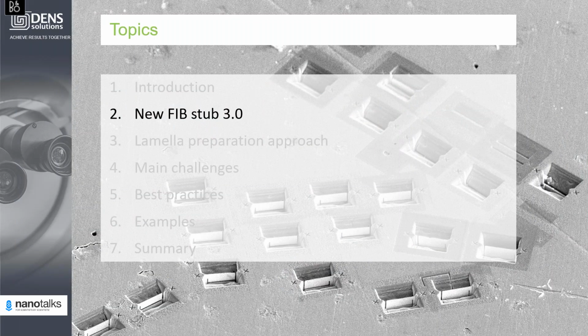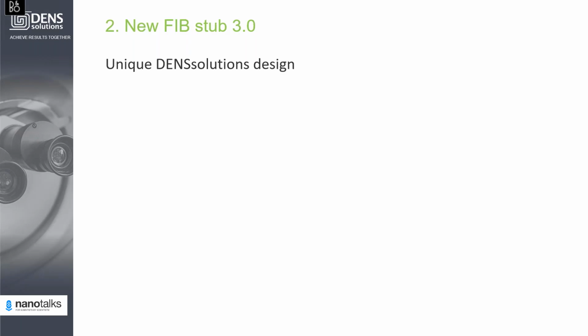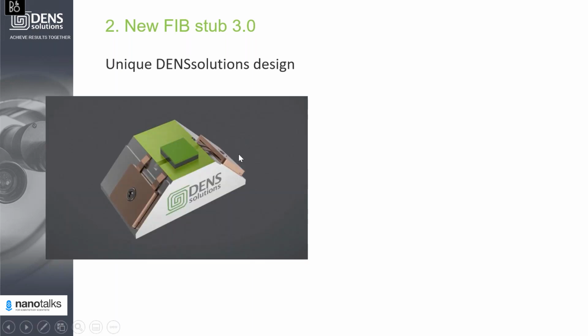So now we're moving to our new FIB stub. Our approach to prepare a FIB lamella is slightly different. We use a so-called FIB stub, which you can see here. The FIB stub is basically a modified SEM stub on which you can put both the sample and the chip at the same time, and the aim is to facilitate the sample preparation. We have a flat side where you put the sample. Having the flat geometry is advantageous for the user, because any FIB operator works in a flat geometry. So everyone will know how to do at least the first part of the sample preparation process.